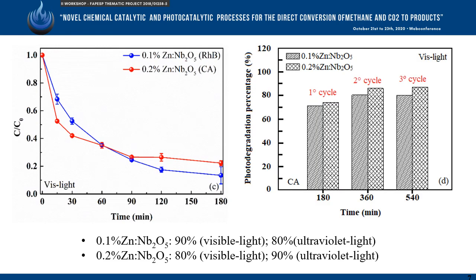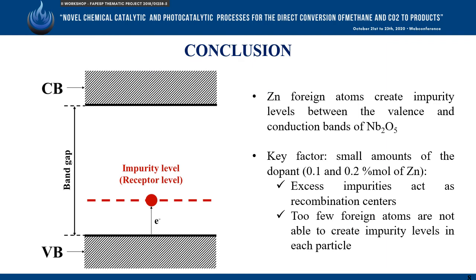Another important point is that the photodegradation percentage remained practically constant after the first cycle. The results discussed in this work indicated that small contents of zinc were enough to considerably decrease the band gap of niobium pentoxide and activate the semiconductor under visible illumination. This happens because zinc atoms create impurity levels between the valence band and conduction band of niobium pentoxide. Therefore, less energy is needed to promote one electron from the valence band to the impurity level than from the valence band to the conduction band.